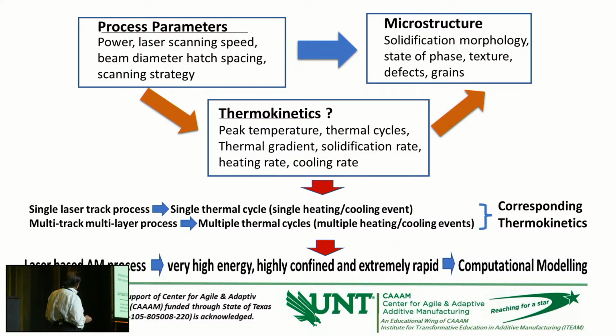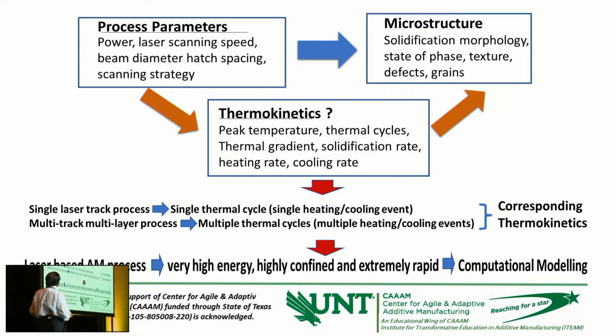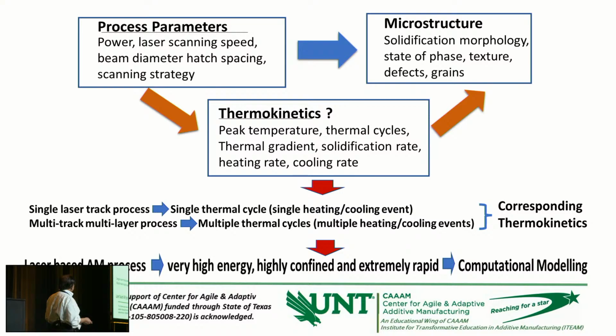These are the major parameters associated with the laser-based AM process, and the material after printing goes through solidification. Depending upon the combination of these parameters, you get a different solidification morphology in the printed component. It also controls the state of the phase, because the kinetics of the process will control the type of phase produced. It also controls the crystallographic texture depending upon the thermokinetics of the process, and it also sometimes brings in defects in the component, because the process is so rapid that it freezes the material and sometimes leaves behind porosity. It also controls the grain shape and size, the grain morphology. All these things are affected by the combination of parameters chosen during AM printing.